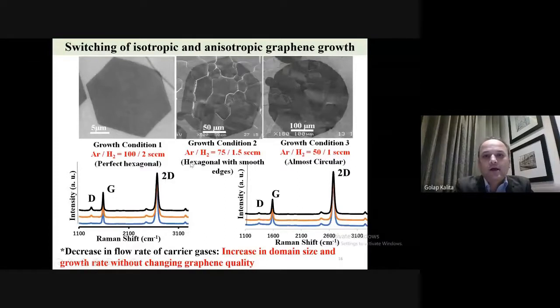But when you have half the amount of gas, this time the precursor is moving much slower. So you have much higher interaction time of the precursor and the substrate, so more precursor on the substrate. So you can have a round shape growth of the crystal, isotropic. So here we show that by controlling the amount of gas put into the CVD process, we can control the amount of precursor flowing on the substrate surface, and by that we can tune the isotropic or anisotropic growth.